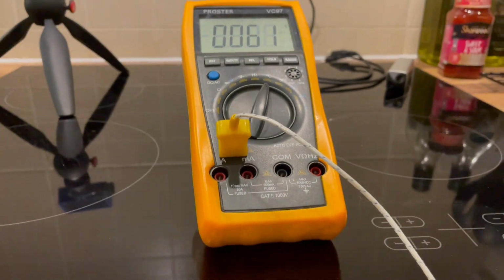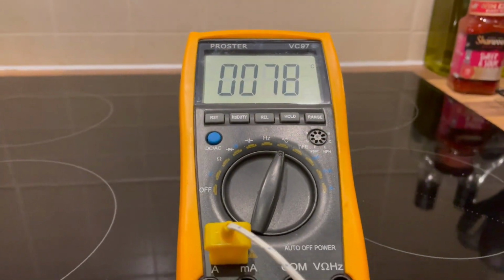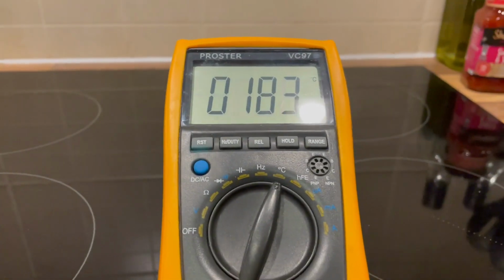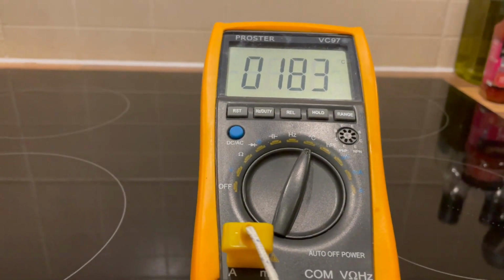Okay, so breaking news, 61 degrees. We've just come up to 60 for 2 minutes and the PLA is gone. Okay, so we're heading towards 80 and the PETG is out, it's gone. Okay, so the nylon's now showing visible signs of sagging. It's clearly sagging, but to be fair, it is at 183 degrees centigrade.